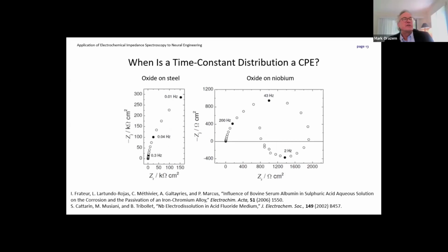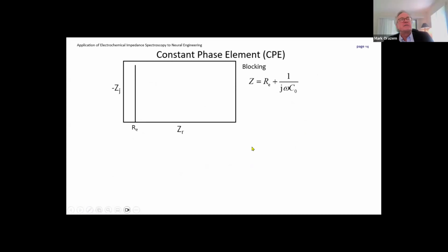The second graphical interpretation thing I wanted to discuss is the question of when is the time constant distribution the constant phase element. I'm showing you here 2 data sets, one for an oxide on steel and the other for an oxide on niobium. Oxide on steel was generated by Isabelle Fratteur, and Sandro Cattarin was the one who organized the measurements for oxide on niobium. And if you don't know what a constant phase element is, it basically is typically used as a way to fit impedance data better.